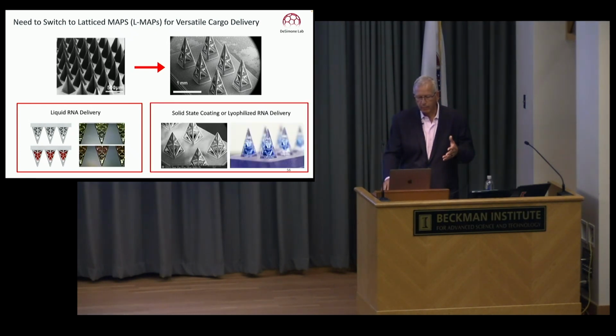Or you can take that liquid and freeze dry it, lyophilize it. And the COVID LNP, lipid nanoparticle vaccine in dry state, is stable at room temperature for 3 months or stable at 4 degrees Celsius for 6 months. But there's a huge cold chain, supply chain issue when it's shipped in liquid form. So this opens up global access and opportunities.